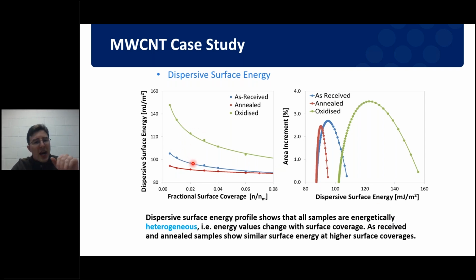So we will start off with our as received. So we can see that all of these samples are heterogeneous. What that means is that their surface energy is changing as a function of fractional coverage. So that means at the most concentrated injection, the one that was aiming for the highest surface coverage, that has a different energy to my most dilute injections. So the concentration of the probes that I'm injecting are influencing the energy that I am measuring. And this is changing sample to sample.